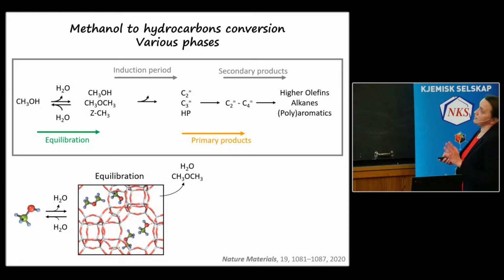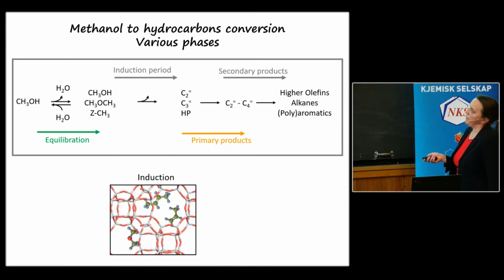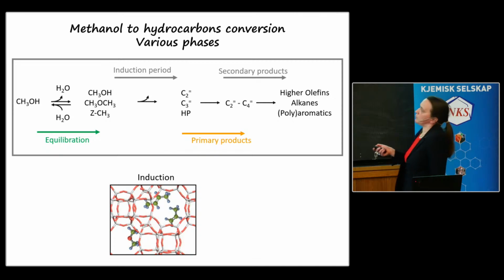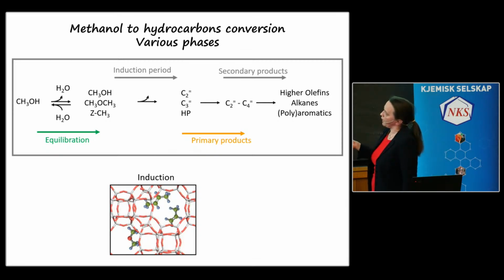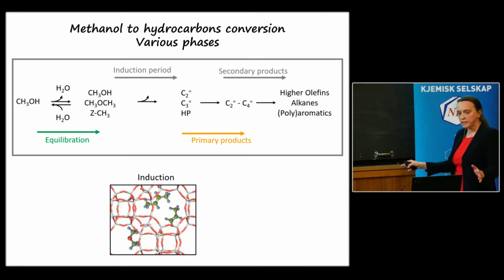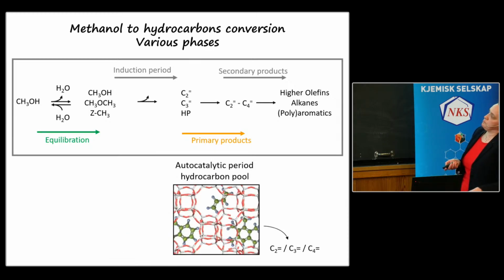So many studies have been done there. If you look at this process, what happens is we start from methanol. What first happens is we have an equilibration phase where we form dimethyl ether and water. So that's what happens here. Then there is an induction phase where we see the formation of the first hydrocarbon pool species, which of course seminal work has been done here in Oslo. So we always refer to many papers here of very good work that has been done here in Oslo to understand this. And then we come to the real active catalyst.